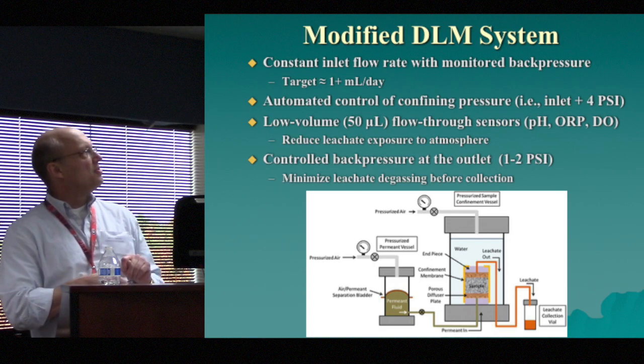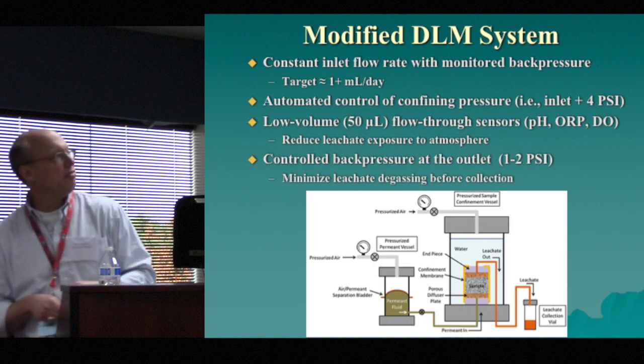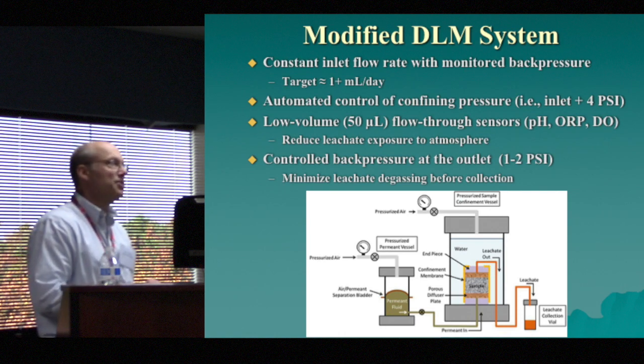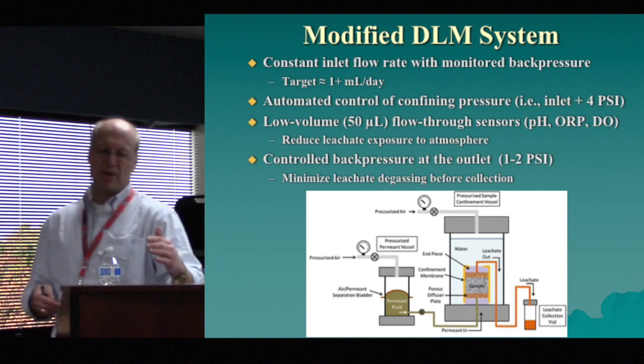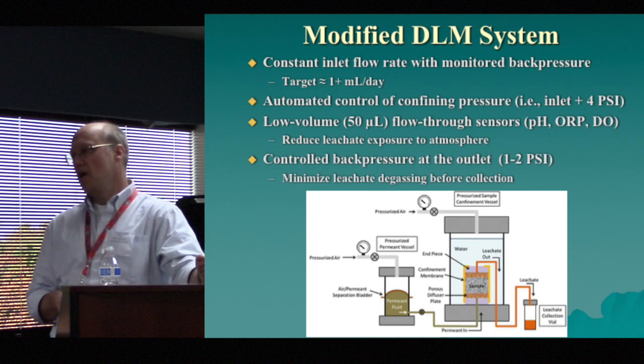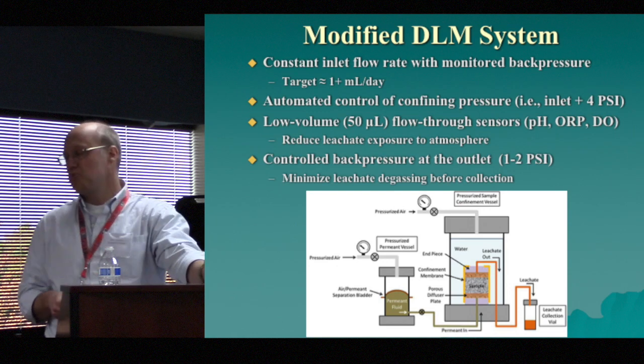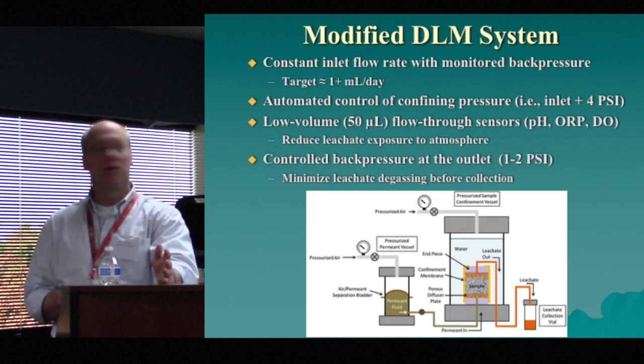We also found some very low volume flow-through electrodes, 50 microliters. So if we're up around 1 mil, we can see significant turnover in a given day, and we don't have this problem of the samples sitting around a long time.